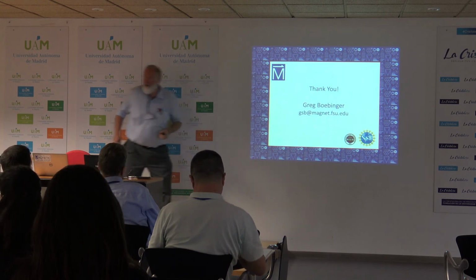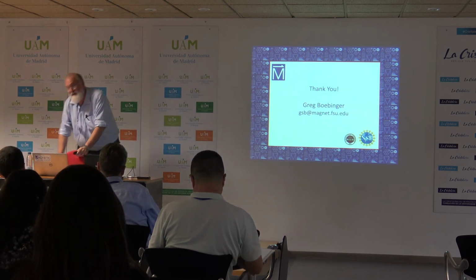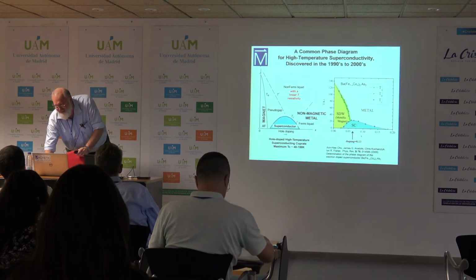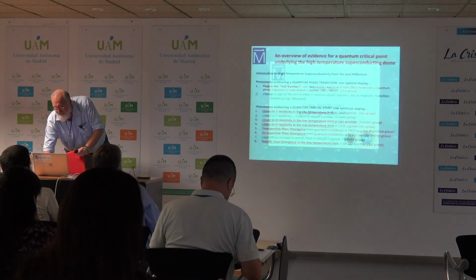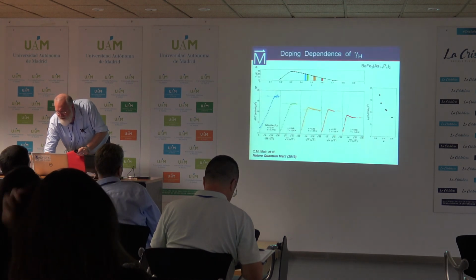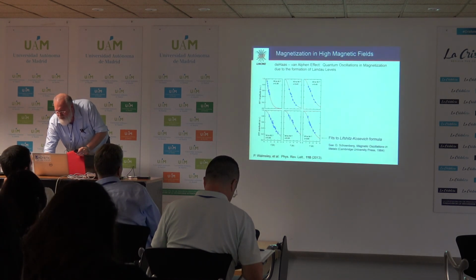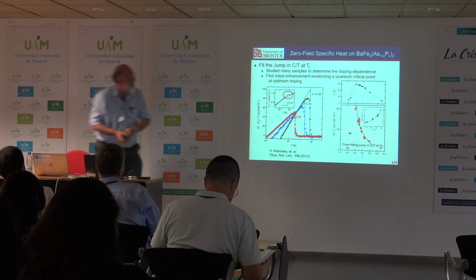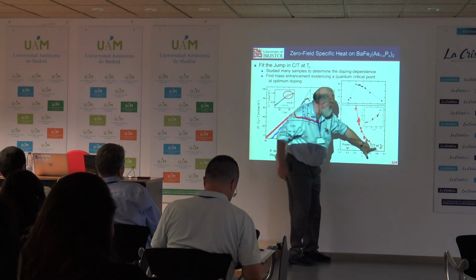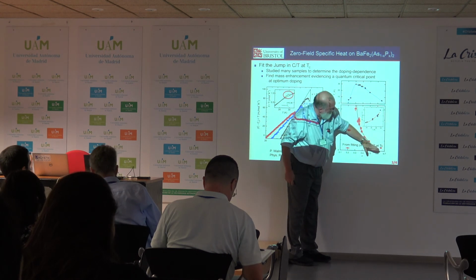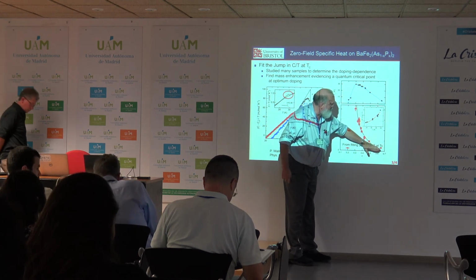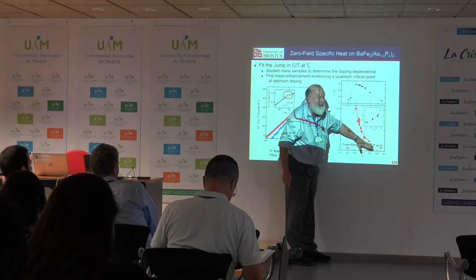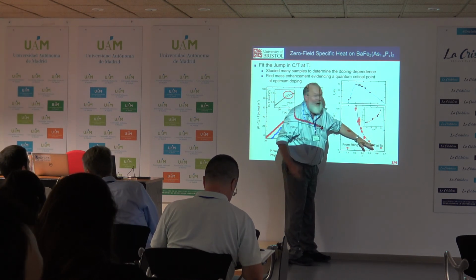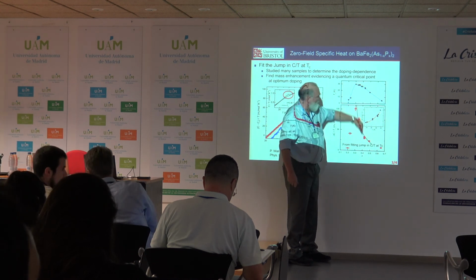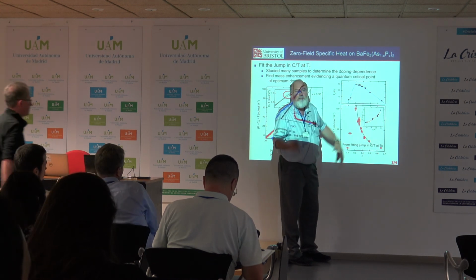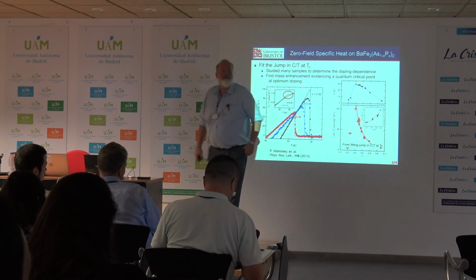So we're out at high enough dopings. We're going to need to retape the wire here. I tripped over it several times, so it's now basically untaped. If we look, for example, here, our data are way out here, at about 0.44. They sort of agree, but our data tend to agree here and be a little bit lower there for reasons I don't understand. I don't know if you have a comment whether this would be due to strong coupling turning on or not.